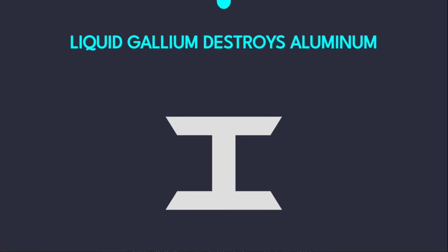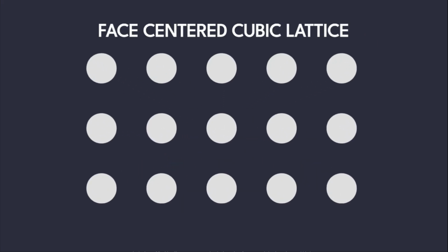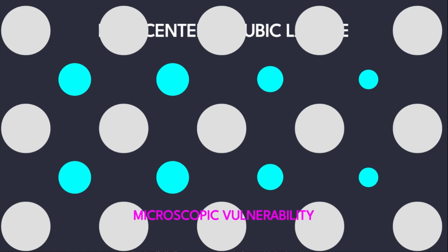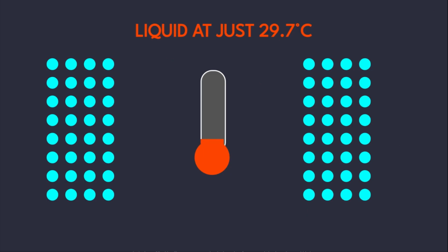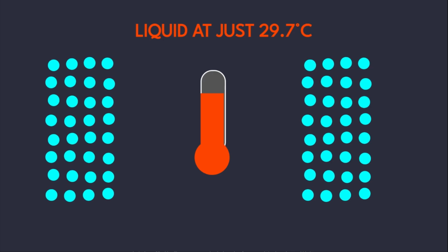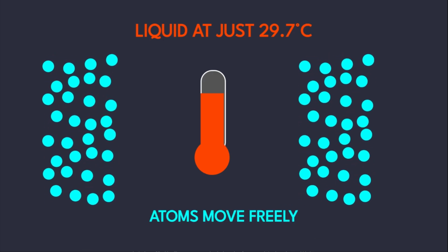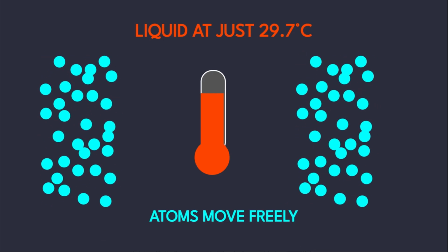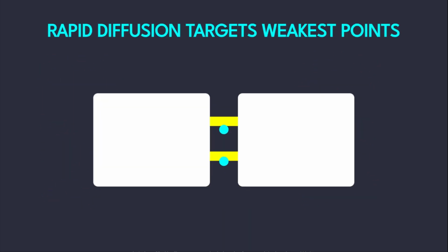A single drop of liquid gallium can compromise the integrity of a structural aluminum beam within hours. While aluminum relies on a dense, face-centered cubic crystal lattice for its high strength-to-weight ratio, gallium exploits a specific vulnerability at the microscopic level. Gallium remains liquid at just 29.7 degrees Celsius, allowing its atoms to move freely. When this liquid touches aluminum, it does not simply sit on the surface like water. It initiates a process of rapid diffusion that targets the weakest points of the metal's internal architecture.